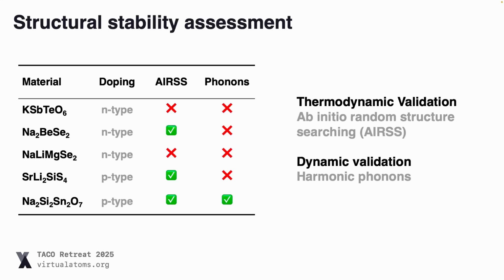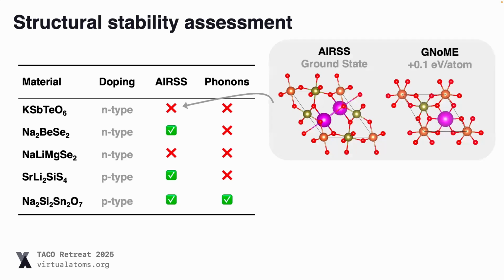And what we found was that in 2 cases, the ground state proposed by GNoME was not the true ground state. And in this case, for example, we found a new ground state which was about 100 meV per atom lower in energy.